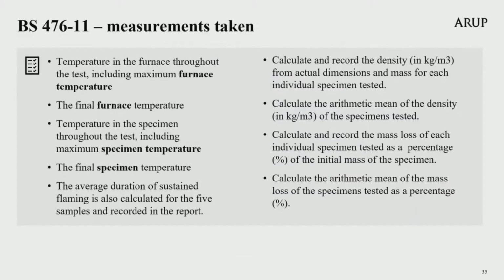Following the test, 2 results are calculated. First, the furnace temperature rise is calculated as the maximum furnace temperature minus the final furnace temperature. Secondly, the specimen temperature rise is calculated by taking the maximum specimen temperature minus the final specimen temperature. This is calculated for each of the 5 specimens and an average value is obtained. The average duration of total sustained flaming is also calculated for the 5 samples and recorded in the report.